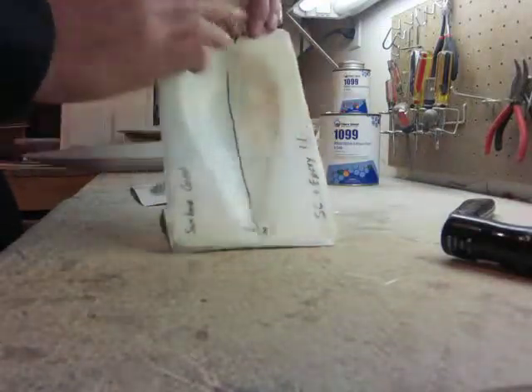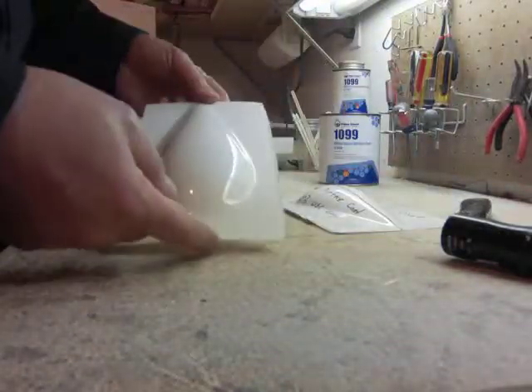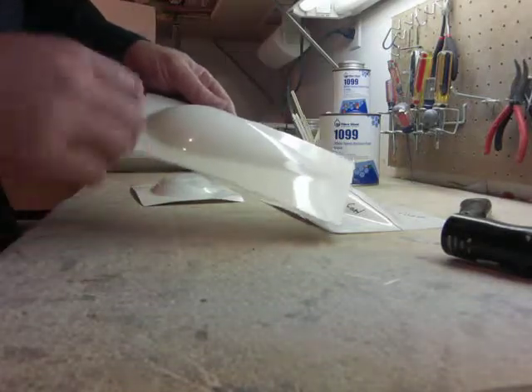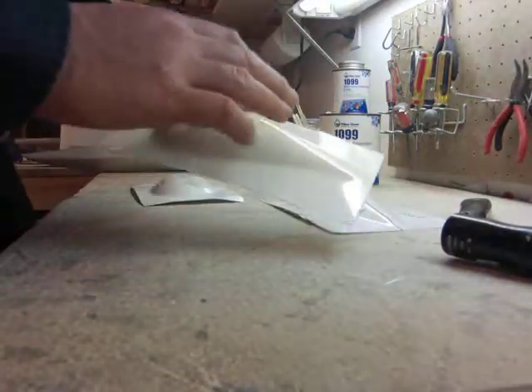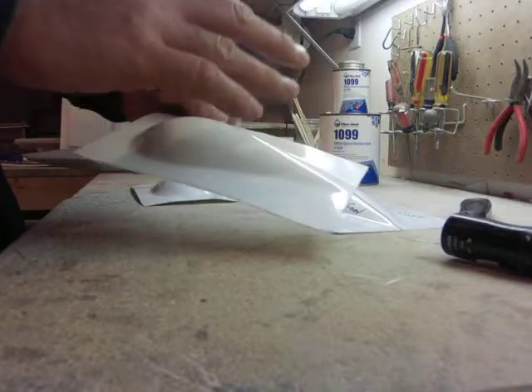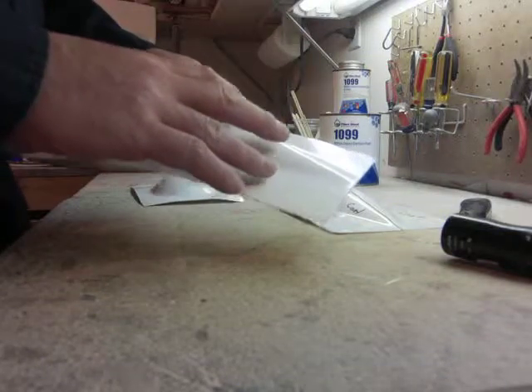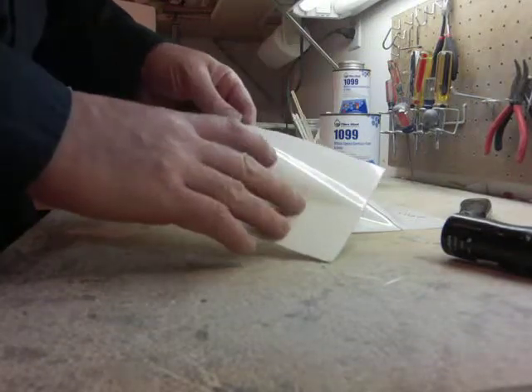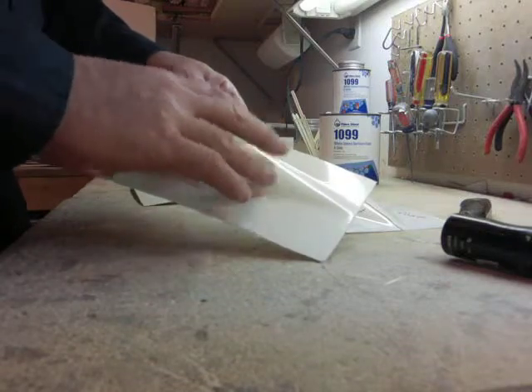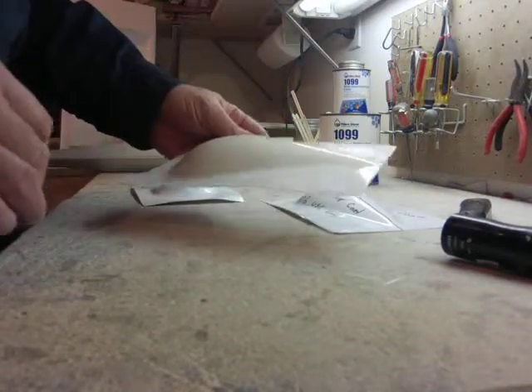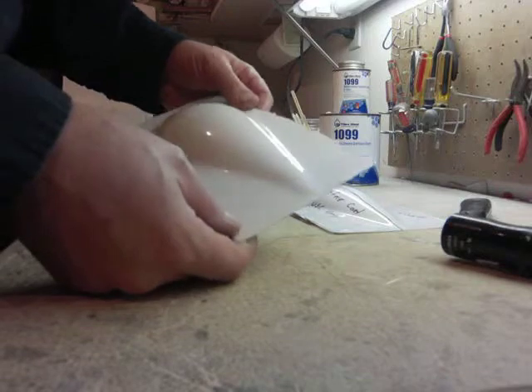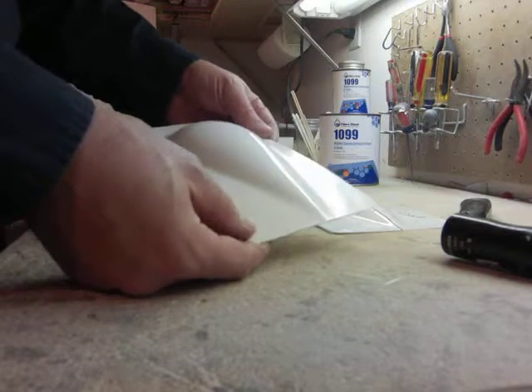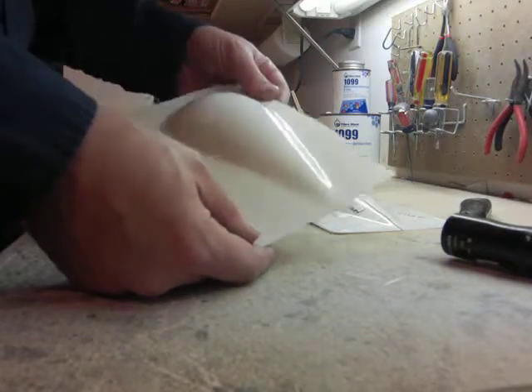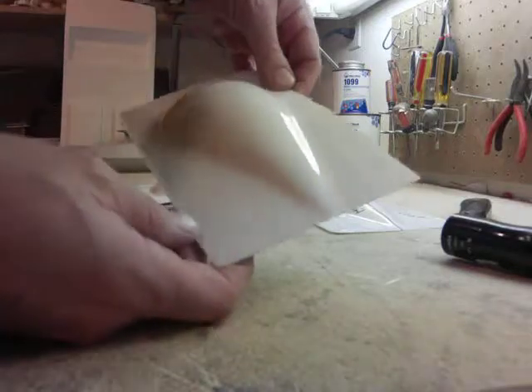Took a long time to dry. Kept having to work it back up where it would settle down. So I made up a second one, and this whole thing was done with 4 parts of tooling gel coat, 1 part of USC epoxy laminating resin mixed together. Worked out pretty good. It was still actually pretty thin. So a 20% epoxy thinning of the epoxy surface coat really cut it quite a bit.